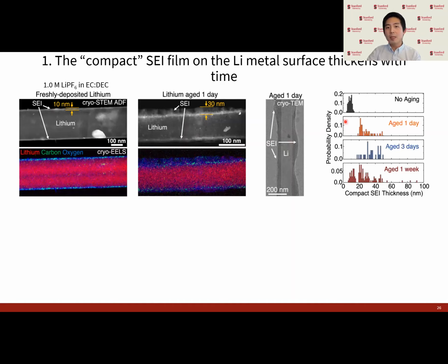By taking a lot of measurements, we can start to get statistics on this thickening trend, and we can see that the growth is indeed highly irregular. And these measurements are all for this LiPF6 in EC/DEC, which is a fairly bad electrolyte at cycling, but among the better ones at storage.